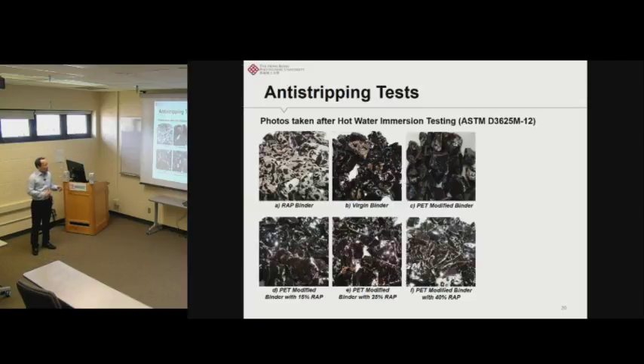So in this slide, you can see the first picture here is actually the aggregate coated with aged RAP binder. You can see what happens after the test. The majority of the binder was lost after the test because of the aging, because of oxidation. Which means the moisture damage resistance is quite poor for the aged RAP binder. And for the second picture, for the virgin binder, we can see it's much better. After the test, we still have most of the binder very well coated on the aggregate surface.